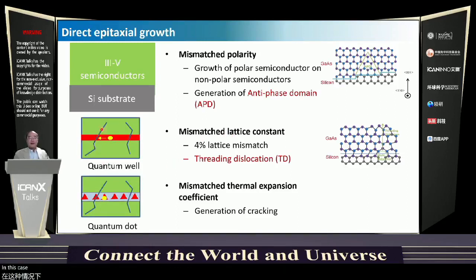In this case, threading dislocation causes degradation, causing non-radiative recombination because carriers are moving freely. So finally, they are captured by the threading dislocation. However, in the case of quantum dot structure, once electron-hole pairs are relaxed inside the quantum dot structure, they are free from the threading dislocation. So therefore, the quality of the quantum dot laser should be much better than that of the quantum well laser.